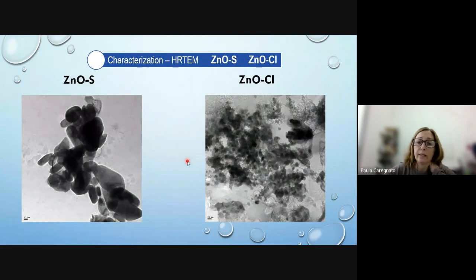Okay, here are the electron microscopy images of the materials obtained from spent alkaline batteries. We can see here the zinc oxide obtained with hydrogen chloride. They are very small compared with the ones obtained with sulfuric acid.